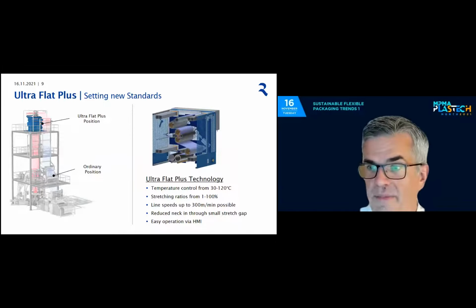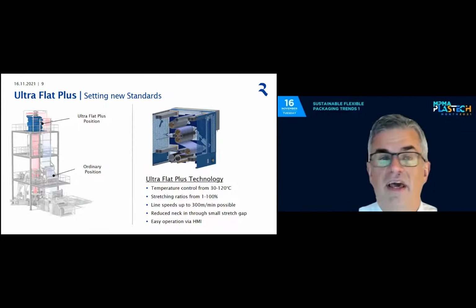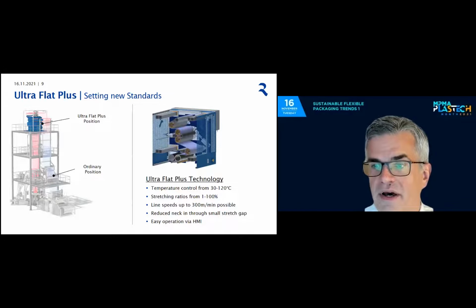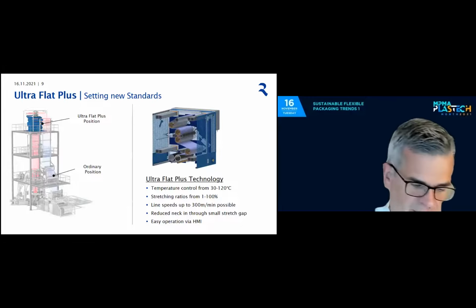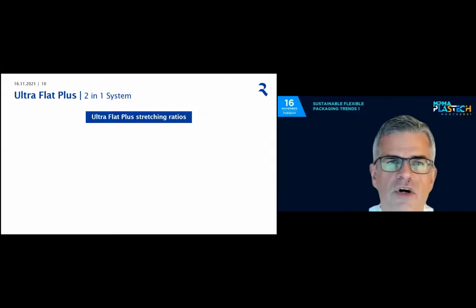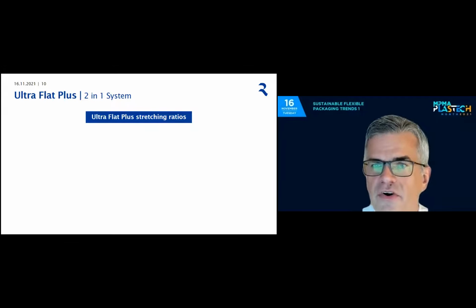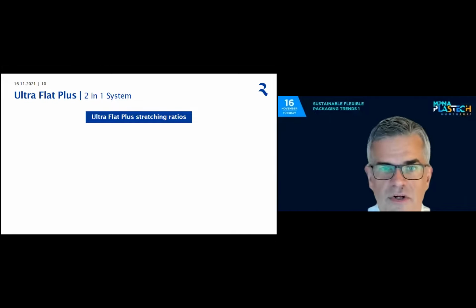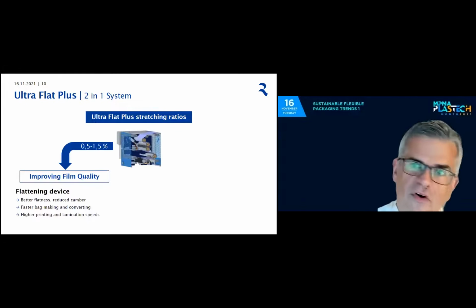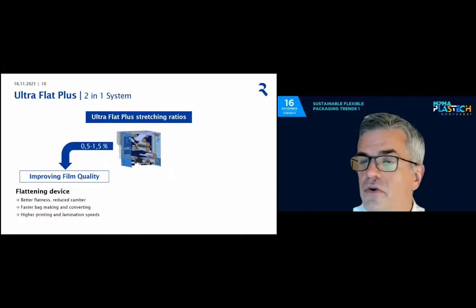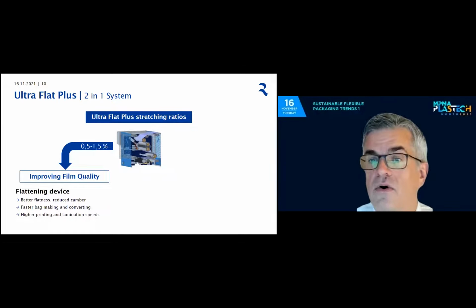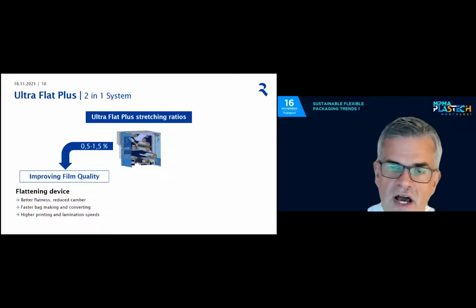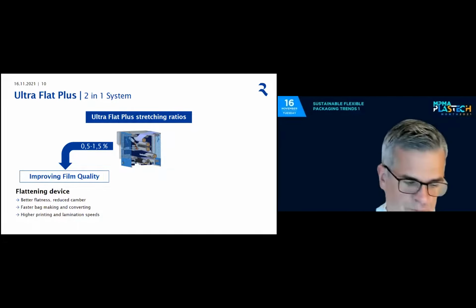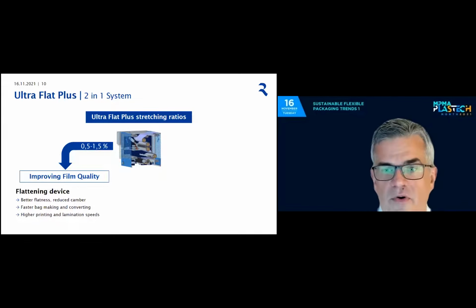And again, each roller has its own temperature circuit. Each roller has its own motor. And the stretching range with this unit is between 1 and 100%. And just one fact which I would like to remind you: you might have heard already of UltraFlat, which is an iron for film to improve flatness. This is for sure included in this device. So if I apply really only 0.5 to 1.5% of stretch, I will reduce camber and get better flatness out of my lamination film, which will allow faster bag making and faster converting operations.